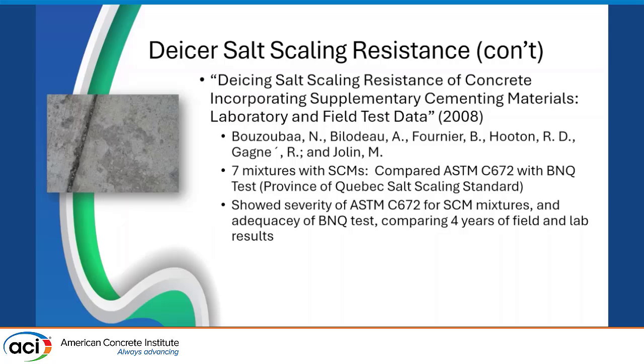there was a relatively new test at the time, called the BNQ test, which is a salt scaling test for Quebec that was developed. That is not the ASTM C672 test that is very harsh, and that particular study found that the BNQ test did a much better job of comparisons with the field studies as opposed to ASTM C672, which was a very, very harsh test.